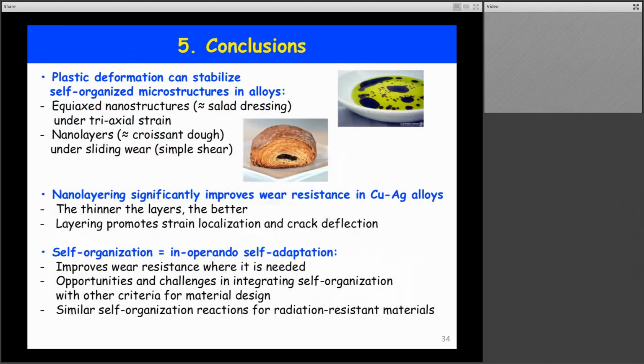So, in summary, I think the key points are organized in these three blue bullet points. I believe I showed you that plastic deformation can stabilize self-organized microstructures in alloys. If we have triaxial stress or strain, these nanostructures tend to be equiaxed, maybe reminiscent of the salad dressing that you obtain by stirring oil and vinegar. On the other hand, if the plastic deformation imposed has a directionality to it, which is the case during sliding wear, where we have simple shear, the resulting nanocomposites tend to form nanolayers, and this is maybe similar to croissant dough, and as we all know, we prefer croissants over salad dressing, so this is better.